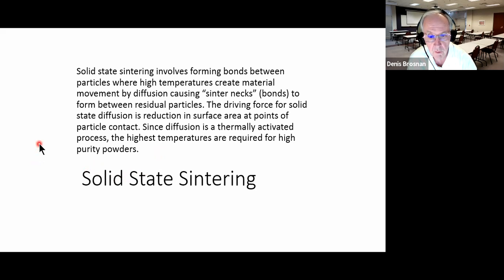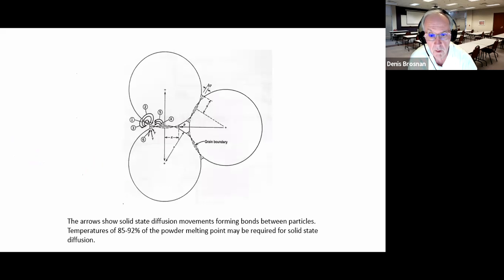You should have taken more courses on this than I will spend time upon here, but solid state sintering is usually a thermally activated process. You have to get up to the temperatures required to form those sinter necks. So temperature and time and reaching a high temperature are very important. Of course, in solid state sintering, we get bulk diffusion from the interior of the particles, in this case, corundum grains and corundum particles, to points of contact. And we get surface diffusion to those points of contact. The object is trying to minimize its surface energy by forming these sinter necks between the particles.